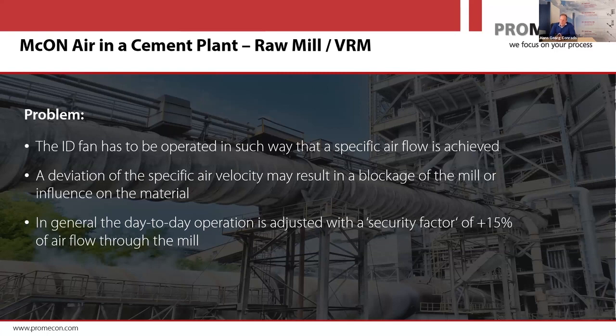Usually operators like to adjust the gas flow a little bit on the high end. And that is exactly because they want to be sure that the mill empties out, that you don't get a drowning mill. These mills have 200, 300 tons per hour. So if a mill like that trips, it's a monster problem. Now, this safety factor costs you a lot of electricity. Of course, everybody knows that. If you have an ID fan, even if it's frequency controlled, you have a ratio between flow and electric power of third order.